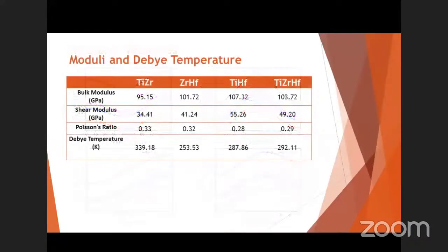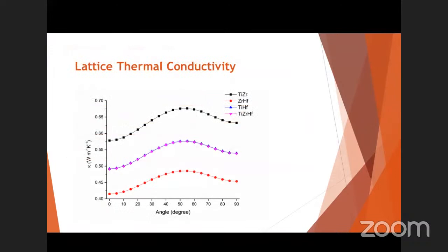These are the elastic moduli of the metals. TiZr shows 95.15 gigapascal. The maximum is for TiHf, which is 107.32, and it also shows a Poisson ratio of 0.28, which is important because the higher the bulk modulus, the stiffer the material. A Poisson ratio of 0.28 shows that we have to pull extra to elongate them. These are the lattice thermal conductivity of these metals, with angle dependence.